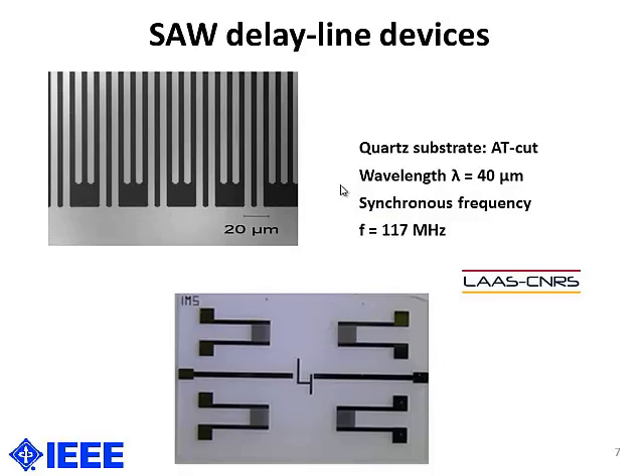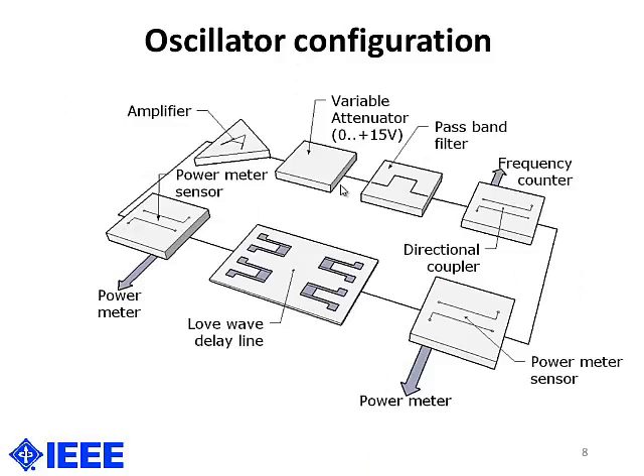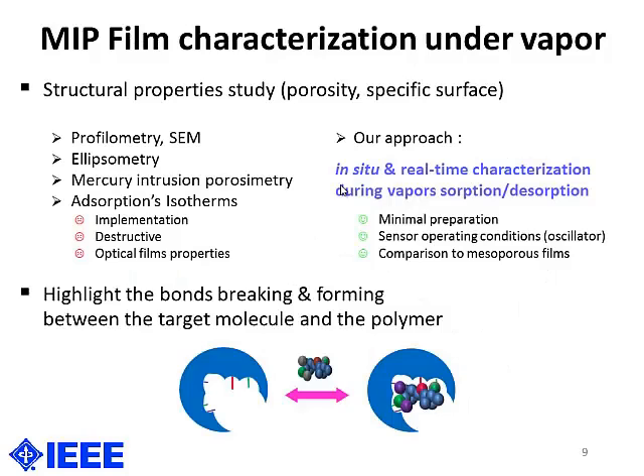These are images of typical structures which have been realized in collaboration with LAAS in Toulouse, with a quartz substrate and wavelengths of 40 micrometers. We achieved a synchronous frequency of about 117 megahertz. This is just a scheme of the electronic oscillating circuit to monitor in real time the synchronous frequency of the device.